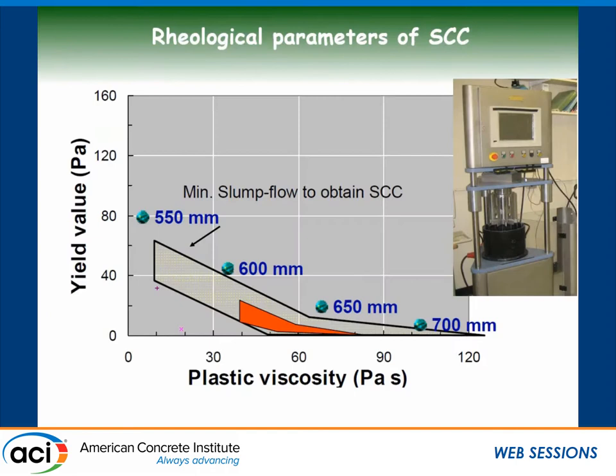Now that makes it easier if we have a rheometer, because with a rheometer like this one here, the ContecS, we can determine the yield stress and the plastic viscosity and draw a zone whereby any point inside it, the concrete will have the requirements that I described. The important requirements here are the ability to fill the formwork without any consolidation, which we call passing ability, and also the stability of the concrete.